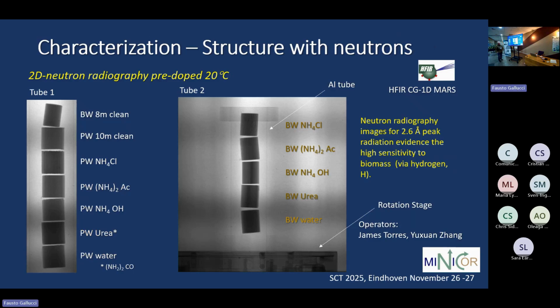Okay, so we combine our experiments between imaging and spectroscopy with neutrons. And what you see with neutrons is that they're hardly affected by the metals here, this aluminum. You see it's transparent, whereas the hydrogen in biomass has a very high absorption contrast. And that you can use: when you heat up and pyrolyze, you lose hydrogen and it gets more and more transparent. And that can be used.